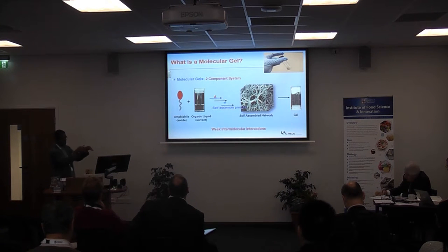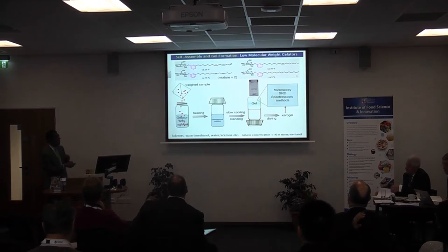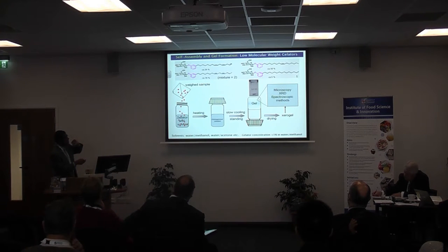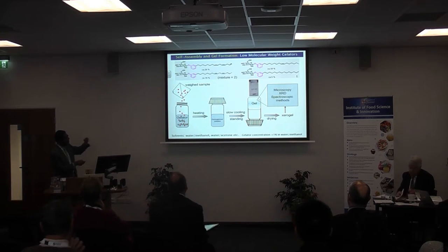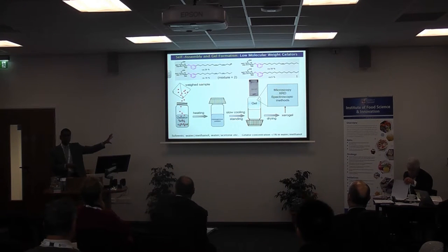That's why most of the videos will be included in these slides, because we want to show that we create a gel in the laboratory, and we make gels from many of these molecules. What we do is we mix with the solvent, we make a homogeneous dispersion, and allow them to assemble together. It's a kind of slow crystallization process, and you can see there is a beautiful gel.